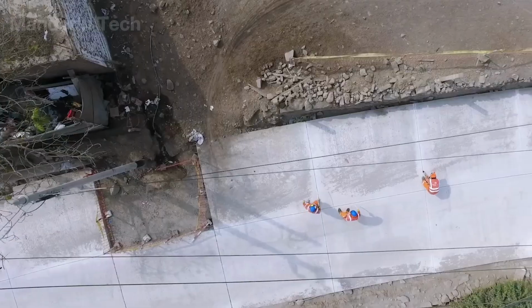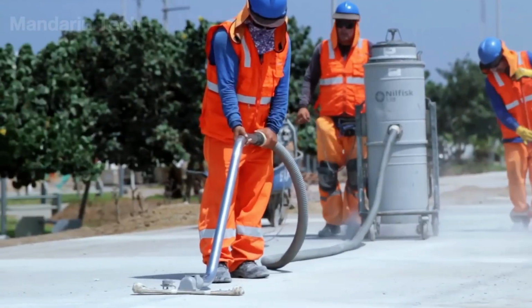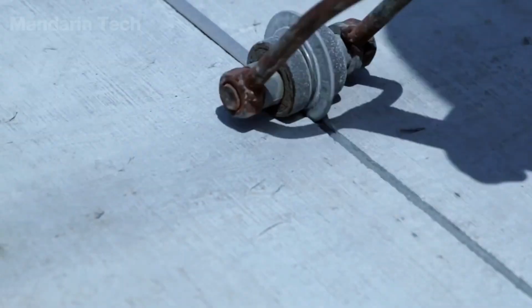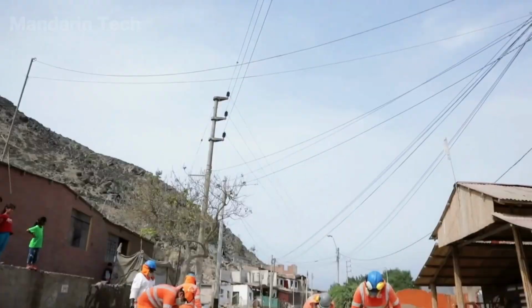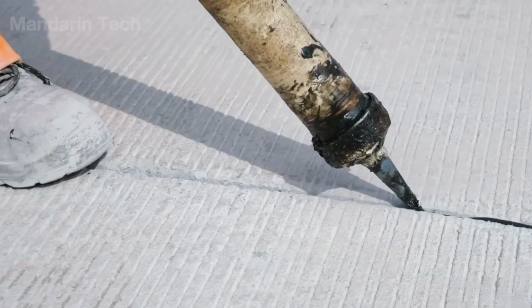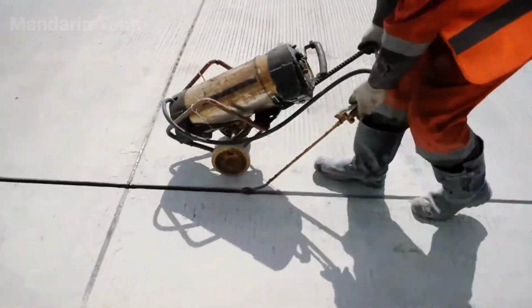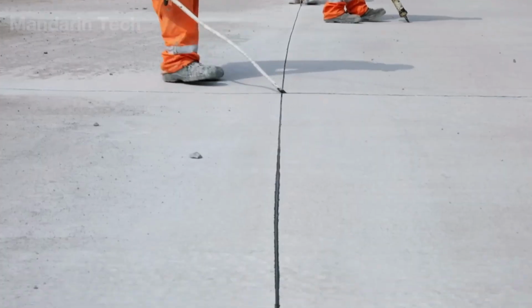A few hours after the joints are cut, workers clean out all the dust and debris inside the gaps, then pump in a layer of special sealant, usually polyurethane, silicone, or bitumen. This sealant keeps water, dirt, and other materials from getting into the joints. Without it, water could seep down through the cracks and cause peeling, cracking, or even damage the base layer underneath.